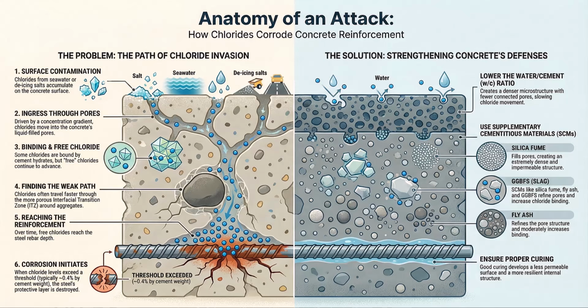And the third challenge. This one feels like it's more about execution than design. It is, and it's arguably the most heartbreaking one. Curing failure. We can design the perfect mix, a 0.35 water binder ratio with 60% SCMs, but if that concrete is not kept wet enough for long enough during that critical early hydration phase, which is a huge challenge in 50-degree heat. A massive challenge. If it's not cured properly, the effective diffusion coefficient, the DF, it just spikes dramatically. The material is fundamentally compromised right out of the formwork. It wastes the entire effort of that expensive, complex mix design.